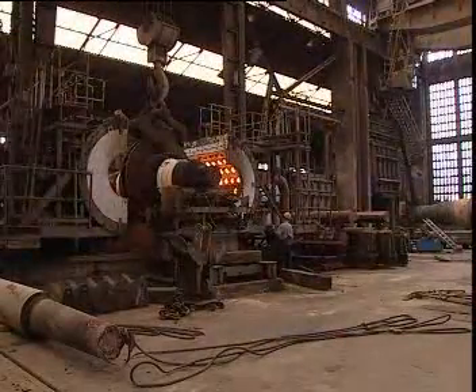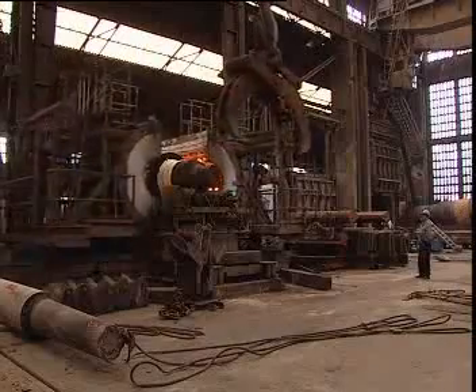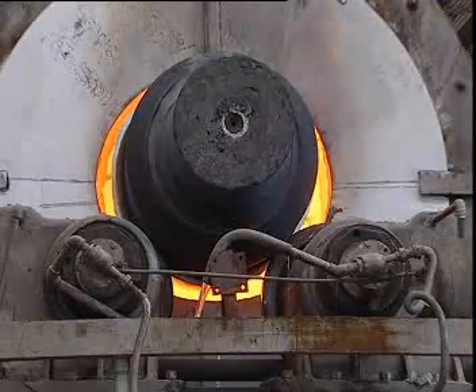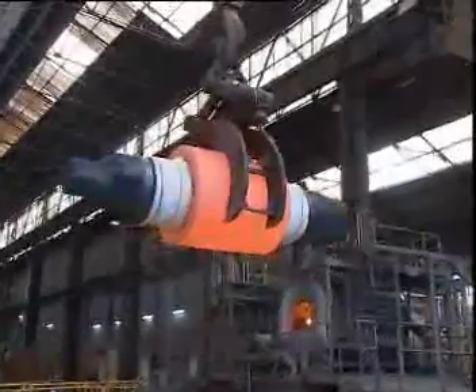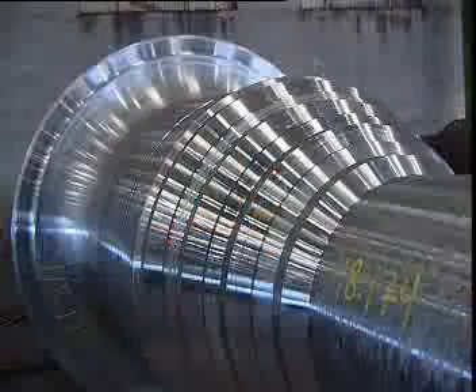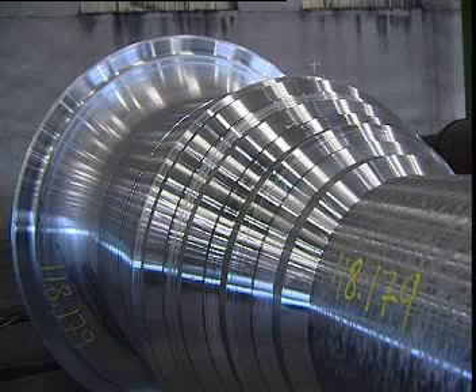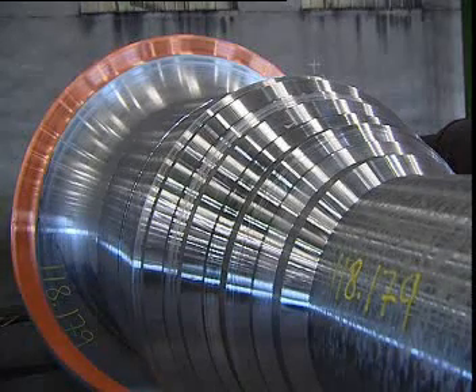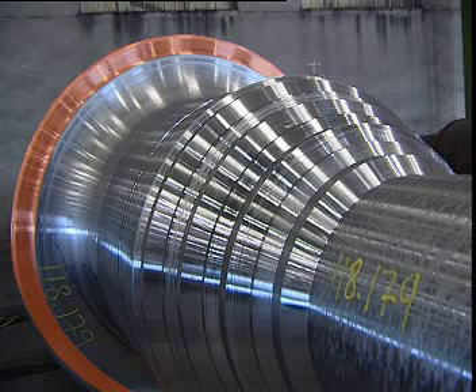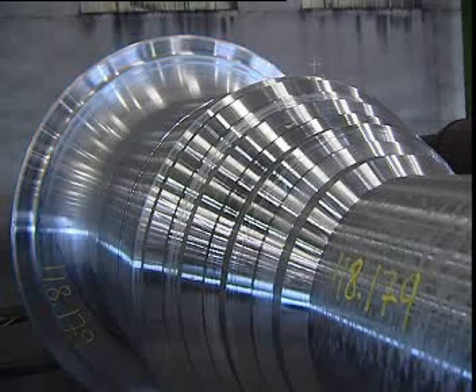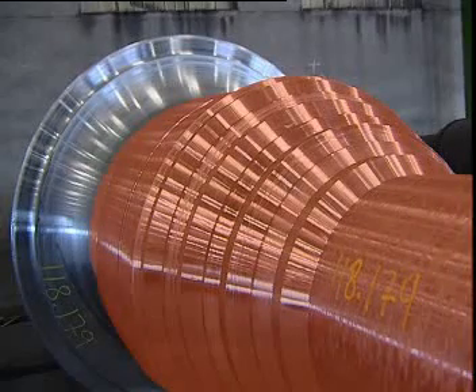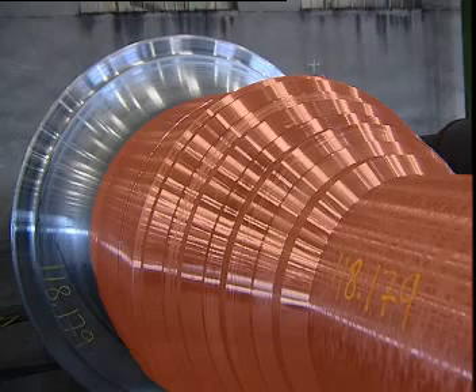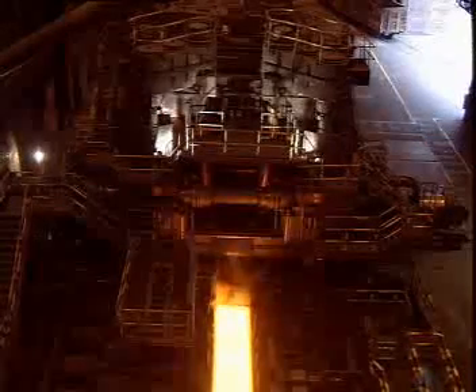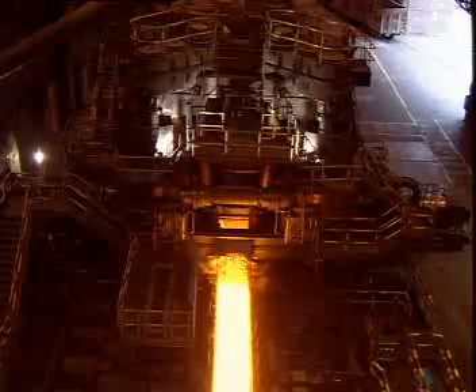A Cellas differential hardening furnace allows us to treat large, chemically homogeneous monoblock pieces, giving them 2 very different structures. For example, this treatment enables our large backup rolls to have an extremely hard and resistant bainitic and martensitic matrix on the working layer. At the same time, a fine pearlitic matrix is obtained on the roll necks and core, making them tough enough to withstand the enormous stresses that they will be subjected to in modern rolling mills.